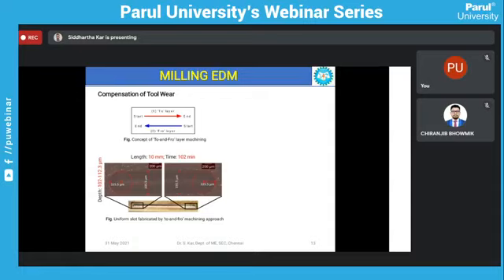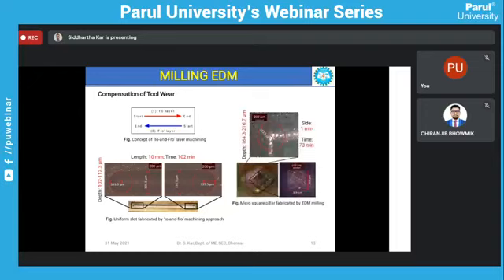Here the depth, as shown here, varies from 102 to 112.3 micrometer, and the width of the slot is almost uniform. It is totally uniform. Then by the same technique, a micro square pillar has been fabricated as shown in the right hand side figure. So here the depth varies from 164.3 to 210 micrometer.